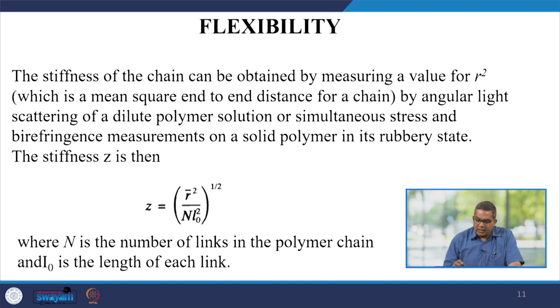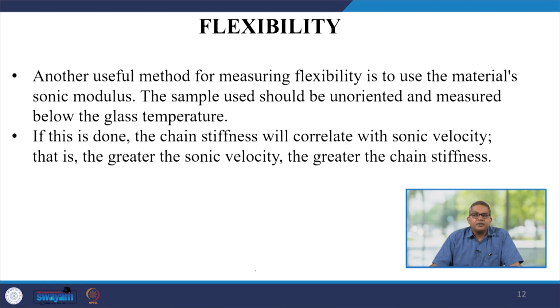Now, this is obtained by angular light scattering of a dilute polymer solution, or by simultaneous stress and birefringence measurements on a solid polymer in its rubbery state. So, this is the mathematical representation for the measurement of stiffness. Here N is the number of links in the polymer chain and L naught is the length of each link. Another useful method for measuring the flexibility is to use the material's sonic modulus.